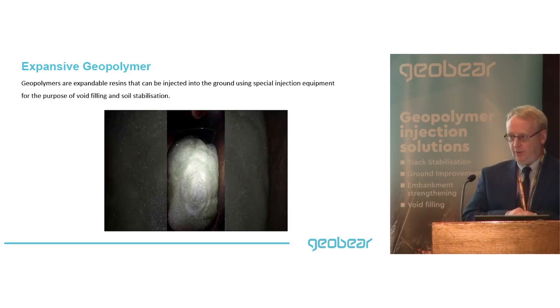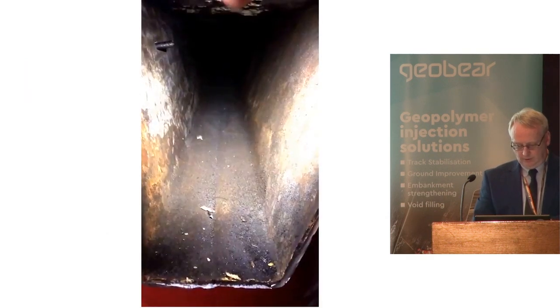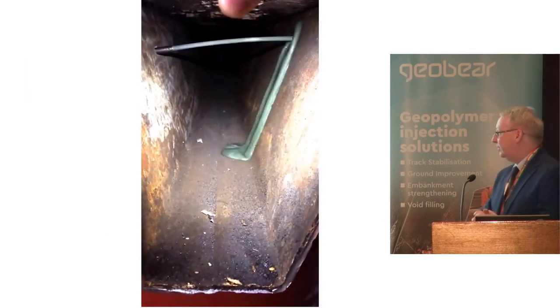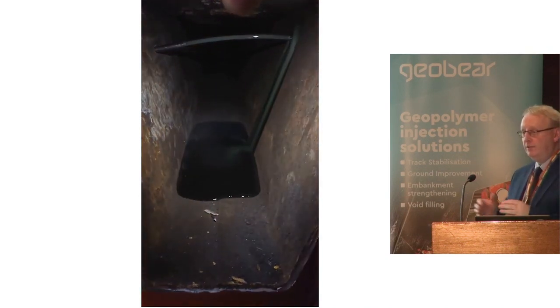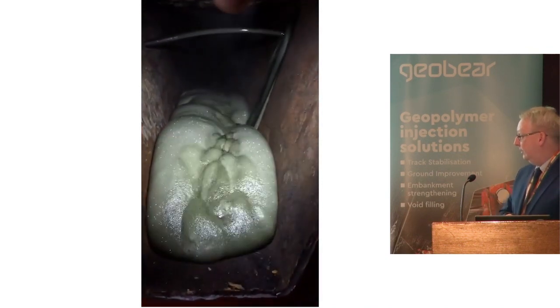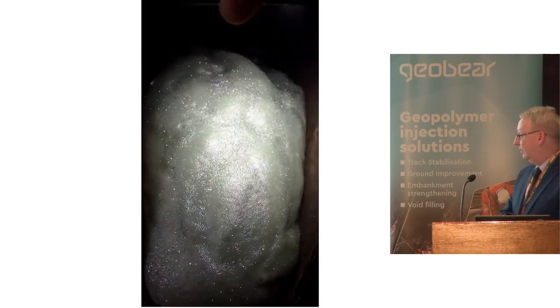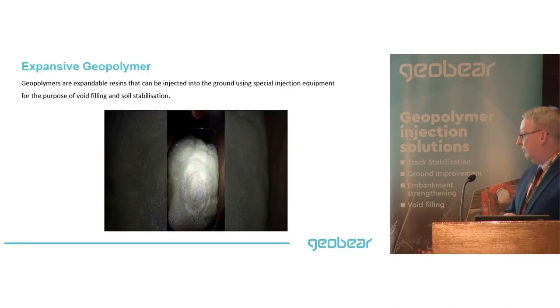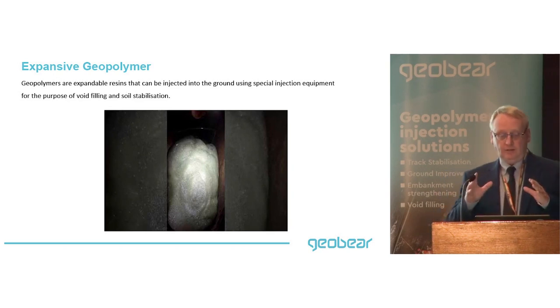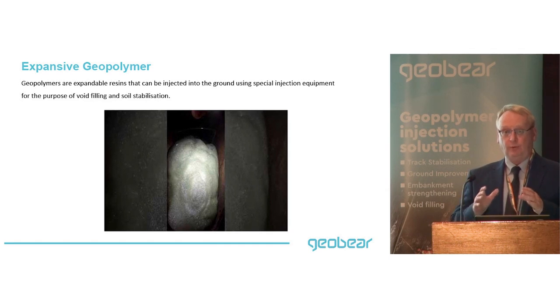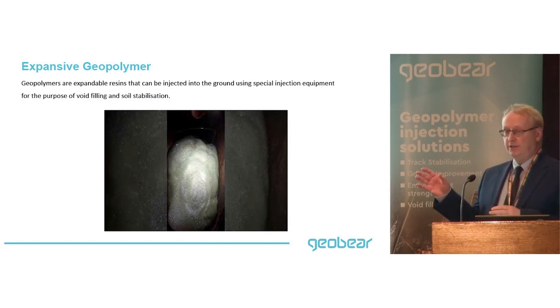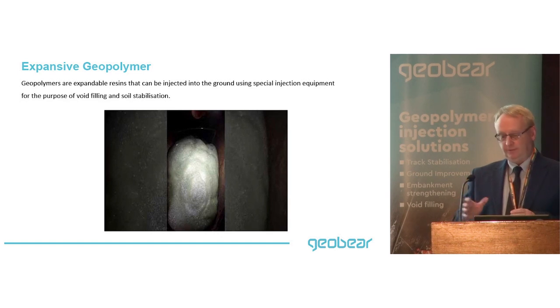There's a short clip here I'm going to show you of us injecting a mixed liquid polymer into a void, and you can see the reaction as it moves forward. So the liquid's going in. After a few seconds, the chemical reaction will start. And it's finished. So this polymer is a void-filled polymer, characterised by a fast chemical reaction, and it's low-density, high-volume, expansive geopolymer.